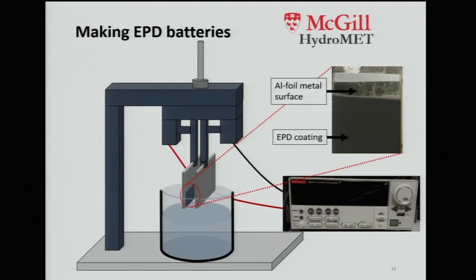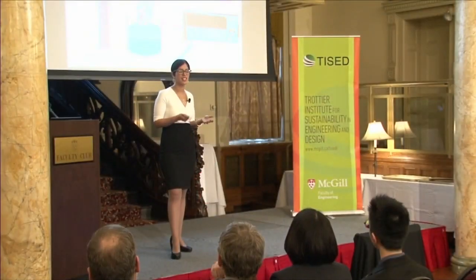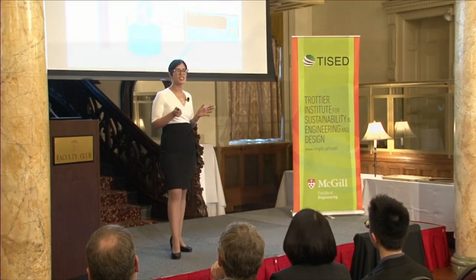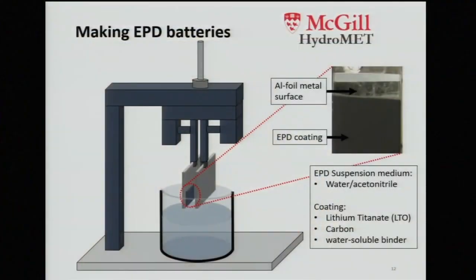So I want to show you how these EPD coatings compare to the conventional coating technique. But to do that, we conducted some tests. And for the tests that I'm going to show, the EPD solution that we used was a mixture of water and acetonitrile. And the particles that we suspended that ultimately became the coating was lithium titanate, which was the lithium-ion material, carbon, which was the conductive material, and a water-soluble binder.